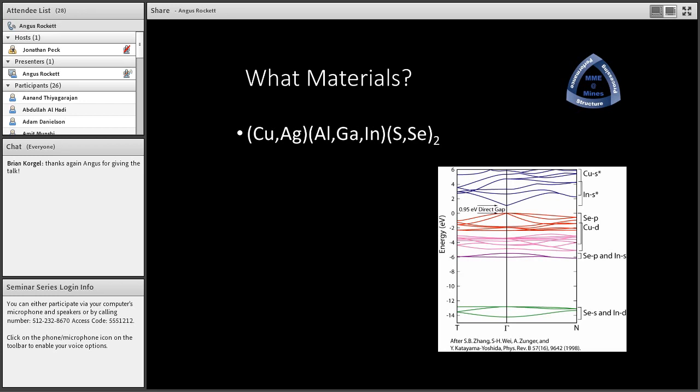You'll notice that there are a lot of curves in these plots because it's a complex band structure. It's a large unit cell, so the band structure is folded back on itself many times. And so we get a fairly high density of states consistent with the high optical absorption in the material.